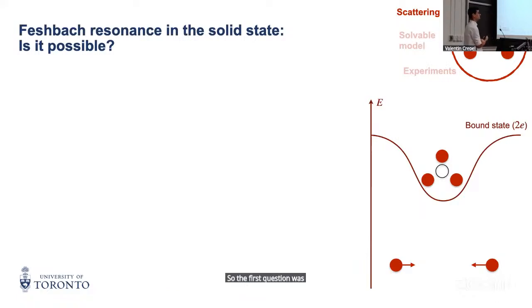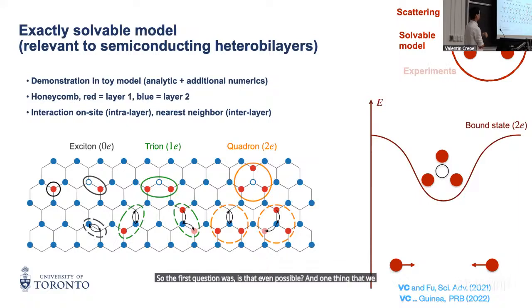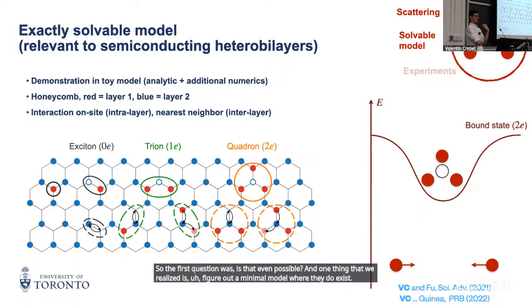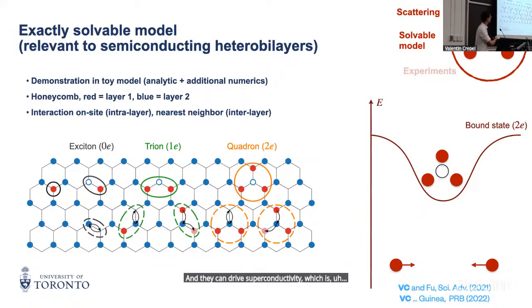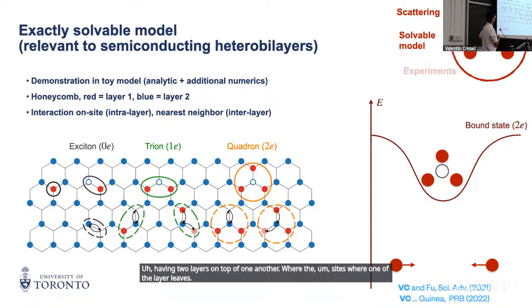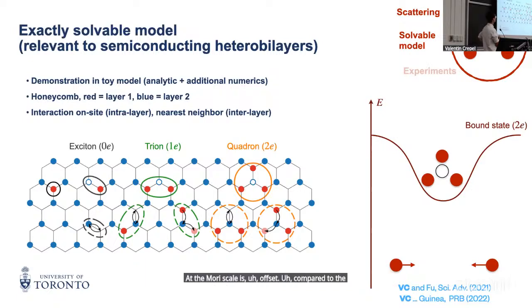So the first question was, is that even possible? And one thing that we realized is to figure out a minimal model where they do exist and they can drive superconductivity, which is what Sergio hinted at during his introduction. So the model is kind of simple, and you can think of it as having two layers on top of one another, where the sites of one of the layers, living at the Moiré scale, are offset compared to the other layer. So each of the blue sites here corresponds to one layer, and it's shifted down in energy. So every site of that layer is filled. And the red dots here belong to the second layer. And the only things we keep in that model are the dominant intra-layer interaction, so on-site interaction, and the inter-layer interaction, nearest neighbor interaction. All right.